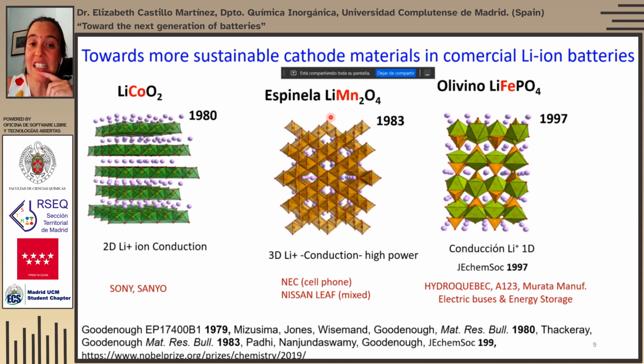The lithium manganese spinel was developed as well in Professor Goodenough's laboratory at Oxford and with his postdoc Mike Thackeray. And this crystal structure has three-dimensional tunnels for lithium-ion diffusion. This higher dimensionality with respect to the layer oxides gives this material higher power and allows it to be used for applications where higher power is required.